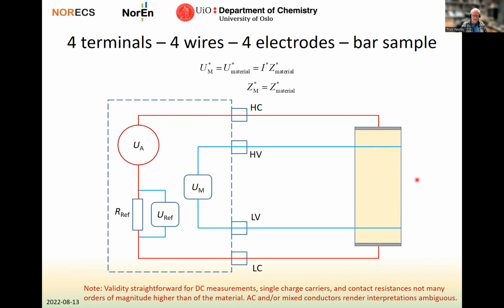The validity of this is straightforward for DC measurements, for single charge carrier, so that there's only one charge carrier that can go through the material, and where the contact resistances here are not many orders of magnitude higher than the resistance or the impedance of the material. Generally speaking, this kind of measurement can eliminate the contact resistance here, but there's a limit to how much resistance there can be here before the current that runs becomes so small that it is hard to measure something in here.